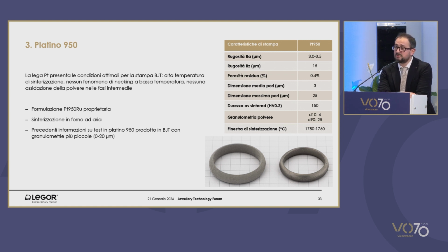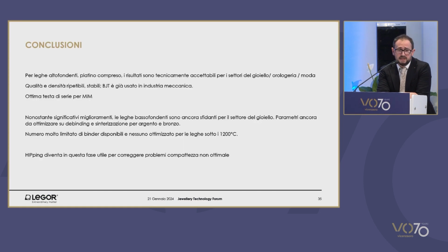Platinum 950. Since last October, we have started printing with this material, which is perfect from many viewpoints. Excellent heat resistance. The sintering phase does not cause any specific problems in terms of the heat level that needs to be reached. The debinding and necking temperatures are based on two mechanisms that are non-competitive. So from the very first printing experiment, we achieved a residual porosity less than 0.5%. So dense items have been obtained with a powder that was slightly coarser than described in the literature, which had 20 micron. So we can actually think about using this powder also to produce products to be sold on the market.